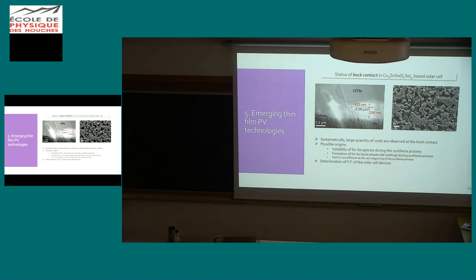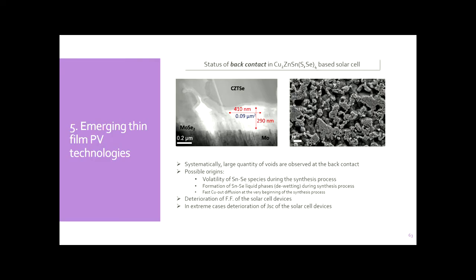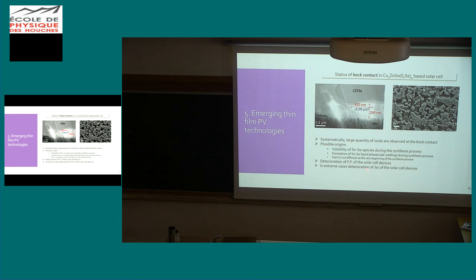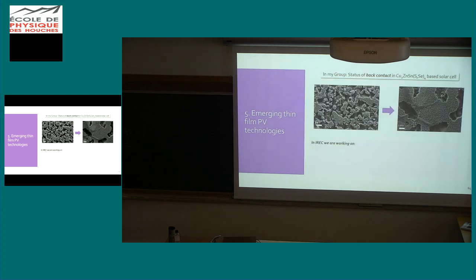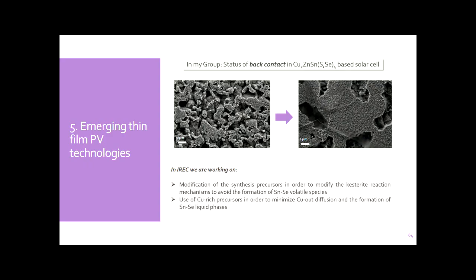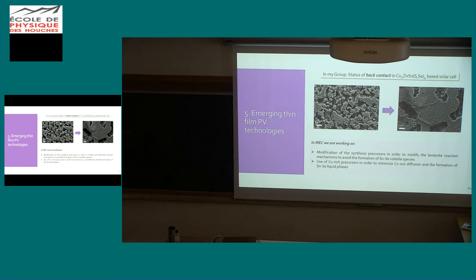And of course you have a deterioration of the fill factor, and in extreme cases you can even observe deterioration in the current, because this absorber here does not have the same thickness as this here or this here. This is maybe 1.1 micron, this is 1.5 micron in this place. So you can have real absorption losses. But we are working on improving that, and there are strategies to change from this to this, that looks a bit better.